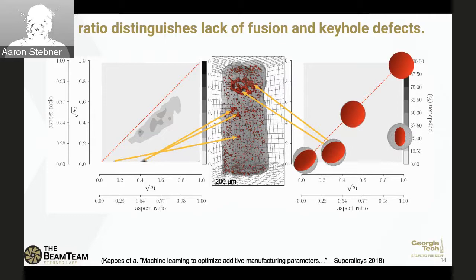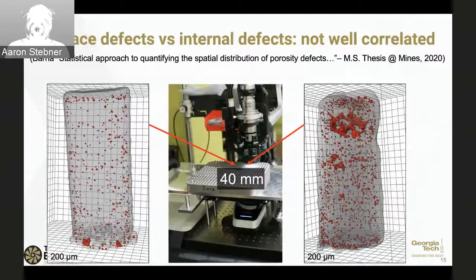Yep. And so the next thing we noticed visually as humans was that if we looked at the surfaces of these pins, oftentimes if there was a really bad defect inside, like on the right-hand side, we'd see really bad surface quality as well. So you can see the surface is much more torturous around that bad defect at the top there on the right side than it is on the left one, which just has smaller surface voids. And so we had another hypothesis that, hey, we can use machine learning between the surface roughness or the surface topology and the porosity inside the part, and we can build a model that will allow us just with optical inspection of the surface to determine whether or not we've got a critical flaw in that part.